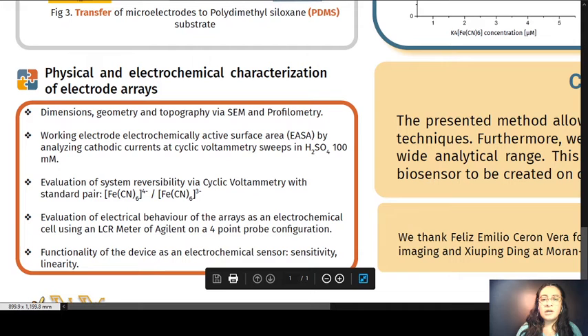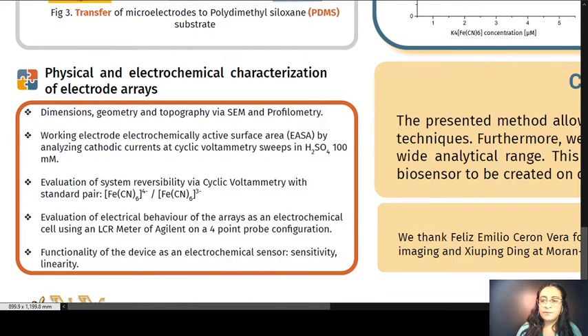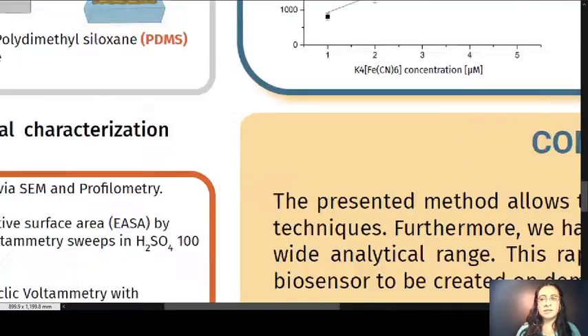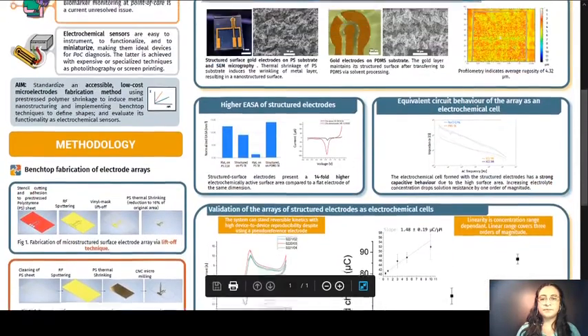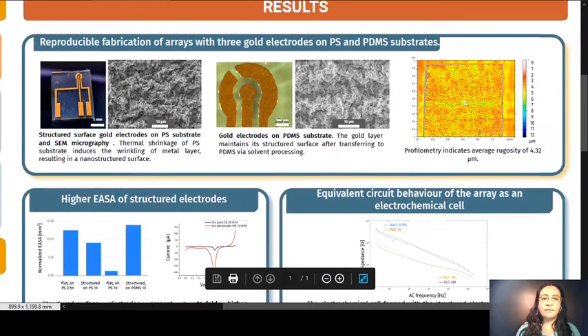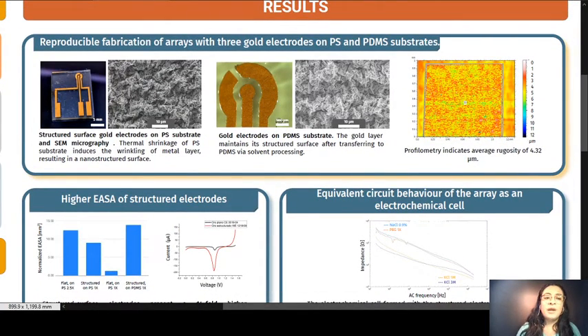We made some physical and electrochemical characterization of the electrodes, and results are going to be discussed next. First, we managed to fabricate 3 electrode arrays on top of polystyrene substrates, and we managed to transfer them onto PDMS substrates with good reproducibility. In electron microscopy images, we analyzed that the wrinkle size was around 340 nanometers, and profilometry indicated that the average rugosity was 4.32 micrometers.